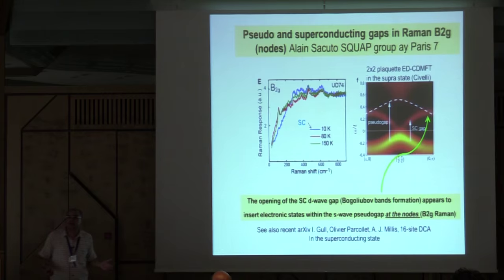Well, if one enters the superconducting state, this is a calculation done at T=0, what will happen if you have a d-wave gap is that the d-wave gap should have this shape, so you see states appearing inside the band of the pseudogap. So this black area, that was my band of the pseudogap, this is the nodal point. Now it's doubled in length. I open a symmetric two Bogoliubov bands. So I should see states reappearing inside the gap. And that's what I observe also in the Raman spectra. What was my pseudogap in the nodal point, so the green, the red, and the superconducting state, you recover spectral weight, which is, in our interpretation, coming from the fact that you put states into the pseudogap at the nodal point. So it seems to me a pretty consistent picture, that perhaps we have something consistent.